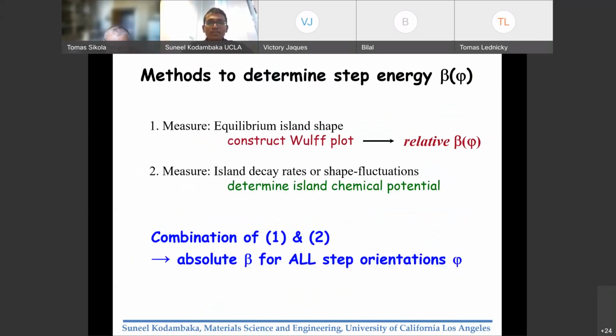Now let me come to another interesting and very important aspect that belongs to surfaces, and that is the step formation energy. I'm going to use this term beta, which is a 2D analog of the three-dimensional surface energy, gamma. The step energy can be a function of the step orientation phi. If it's completely isotropic, the step energy will be the same for all step orientations. But if it's anisotropic, which is the reason that you see square-shaped islands on the 001 surface and triangular-shaped islands on the 111 surface, instead of a completely circular shape, then the step formation energy will vary strongly with the step orientation.